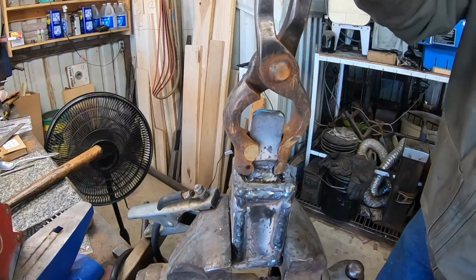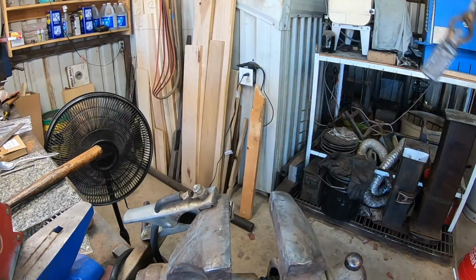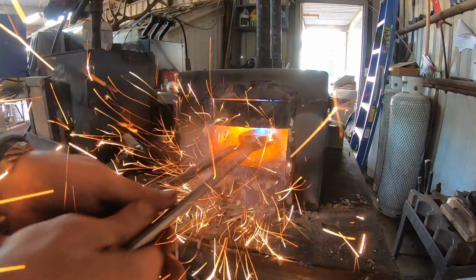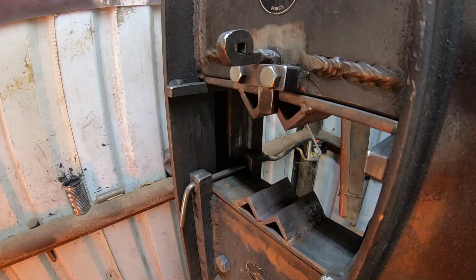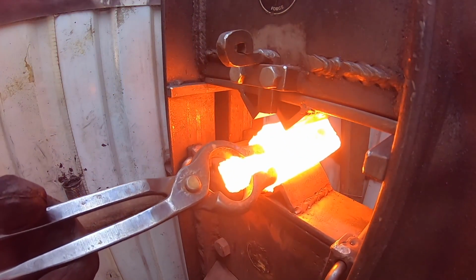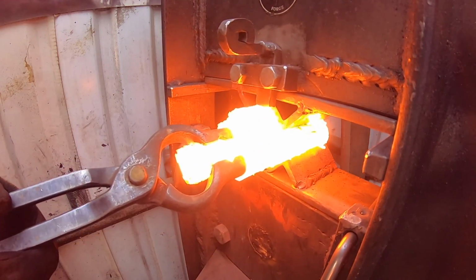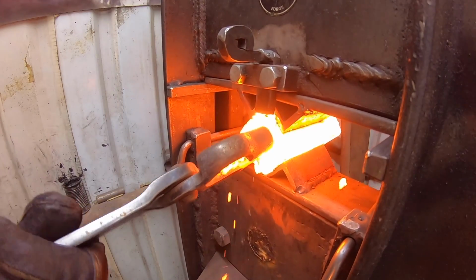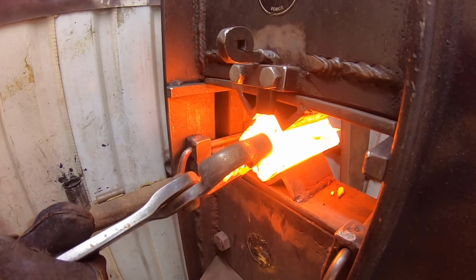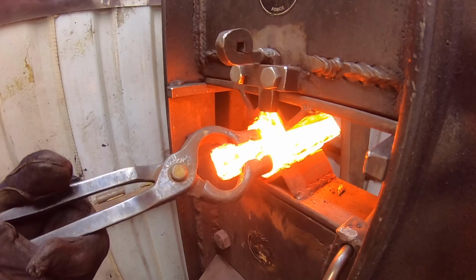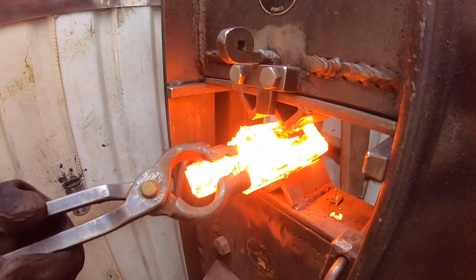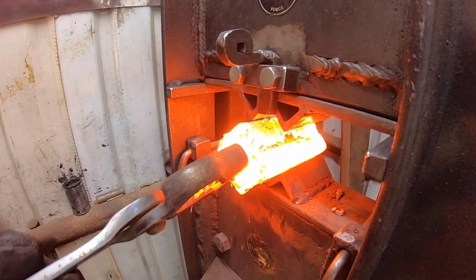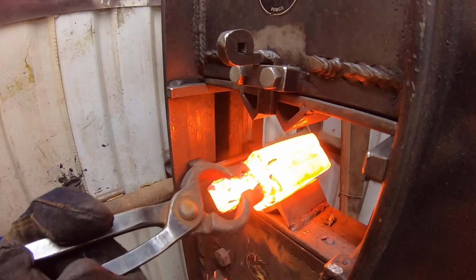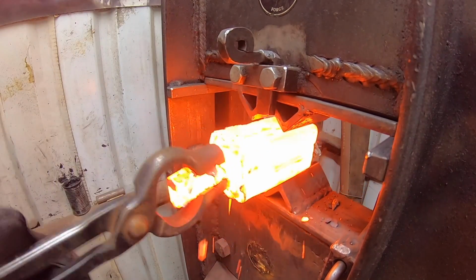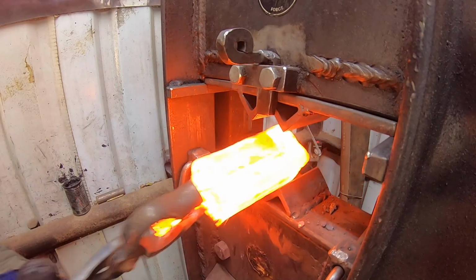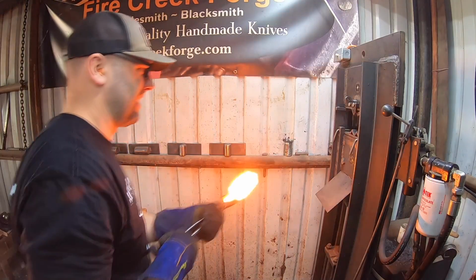We can weld the cap or the top of the canoe on, and everything's in there nice and tight so it doesn't flop around and there's no air pockets. And then we can heat it up and press it together in the forge. This should forge weld everything together with the heat and the pressure together. And the nice thing about a canister is that you don't have to worry about the atmosphere, and so you don't have to put any flux on your steel. It's protected from the oxygen, and everything should go together pretty nicely.